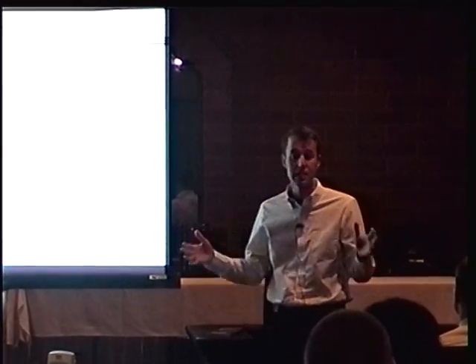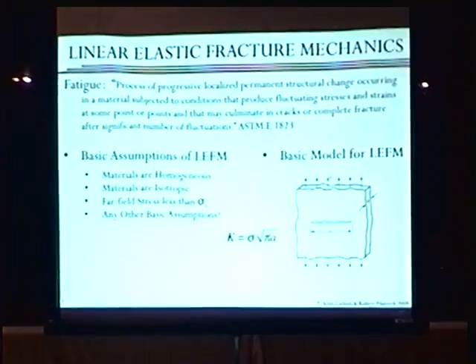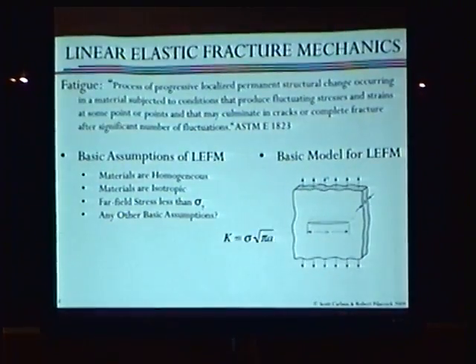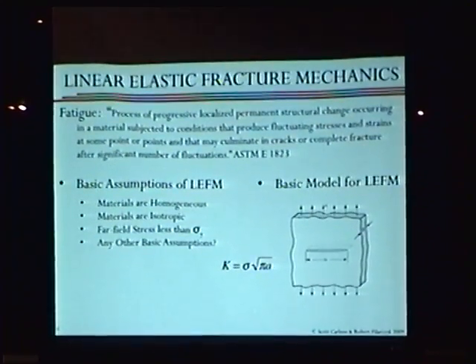So in order to deal with fatigue in structures or in pipelines or anything, we use what's called linear elastic fracture mechanics for the vast majority of what we do. Linear elastic fracture mechanics uses a basic, simple model. In that model, shown here on the right, it's an infinite plate in pure tension with a center crack in the middle of it. And we use a really, in my opinion, a really great equation.